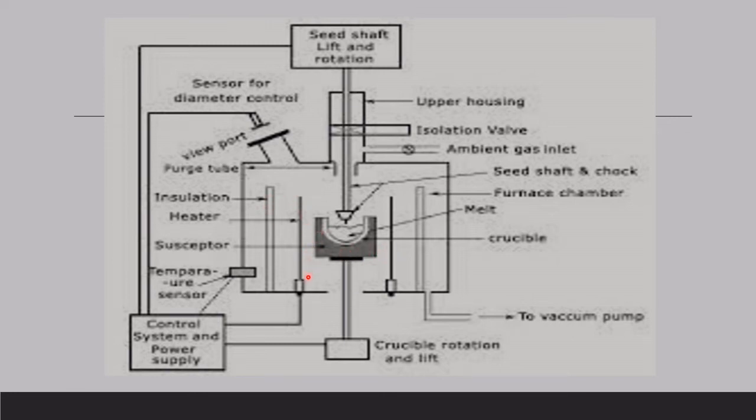This is the heater. This is also a heater and this is also a heater. Heating is done by radio frequency, so this is RF heating. Usually we use a very high purity graphite heater. So these are the things inside the furnace: a quartz crucible, a graphite susceptor, this black rod is the heater, and the cooler for the outer quartz chamber, the quartz envelope.